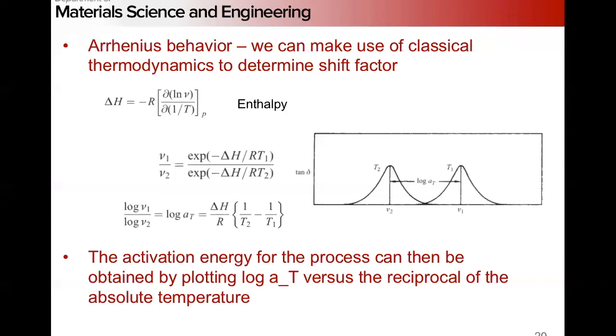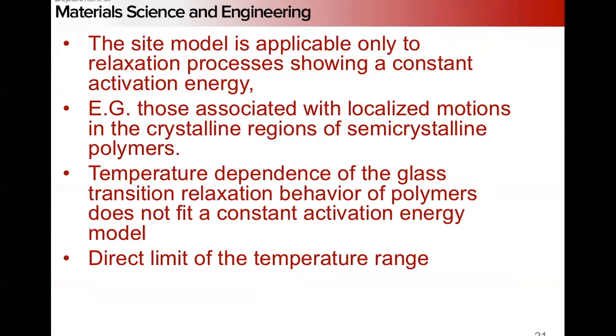So it's kind of an interesting approach, right? We're starting with some simple thermodynamic assumptions and an empirical model, and making a generalization of how to interpret these shift factors. So what are the big assumptions that we need to consider? Here we're really assuming that the relaxation processes have a constant activation energy. If activation energy changes, or we have a mechanistic change of these relaxations, this approach definitely won't work.